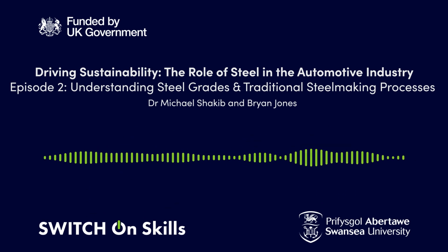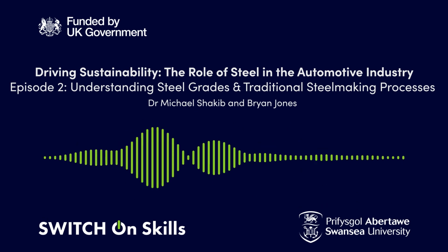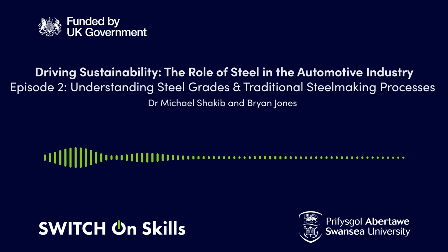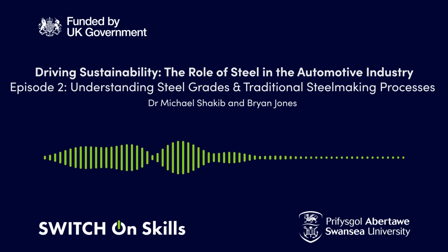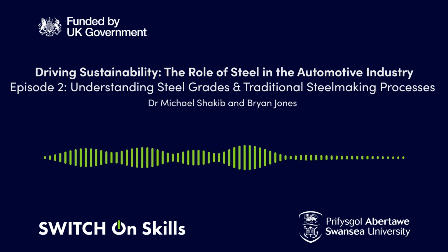By addition of various alloying elements, such as aluminium, titanium, chromium, and so on. Niobium. And now you can end up with, say, 30 or 40 different chemical compositions. And then that moves on to the rolling process. You first of all cast the material into a slab, and then the material is processed through a hot mill, and the processing conditions in the hot mill will vary very significantly depending upon the grade of steel that you want to produce.